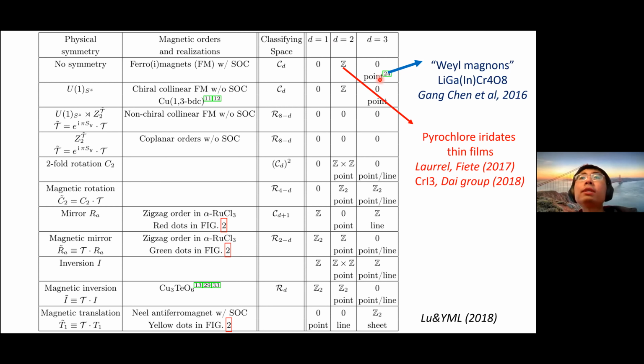For 3 dimensions in this same symmetry class, there is a point touching in the spectrum of the spin wave. These are known as Weyl magnons. They are the analog of the Weyl semi-metal in electronic bands. These Weyl magnons have, for example, been proposed to be realized in the so-called breathing pyrochlore lattice.